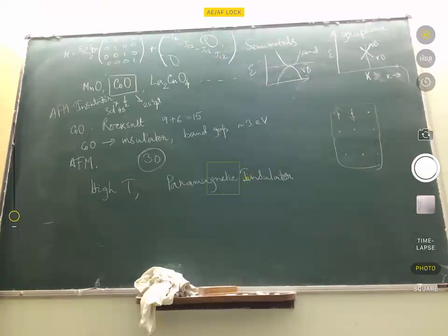So therefore, the unit cell, one can argue, is really double of what we were thinking, because we have to now include both the up and down spin cobalt atoms in our description of the structure. So the unit cell doubles up. So if it doubles up, then you have 30 electrons in the unit cell, not 15 anymore, and one could have an insulator.